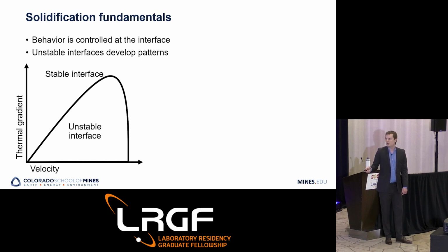And depending on how high your thermal gradient is, you can either drive into that low undercooled liquid and form solid that becomes a perturbation to the solid-liquid interface and destabilizes it, or you can have that interface become stable depending on your thermal gradient. Or if you're solidifying fast enough, if that solid-liquid interface just rips through the liquid, then you don't care what the thermal gradient is anymore because it's solidifying so fast that the atoms don't have time to diffuse away from the solid-liquid interface, and you just freeze the composition in place.